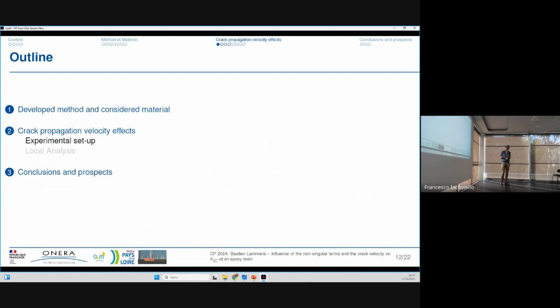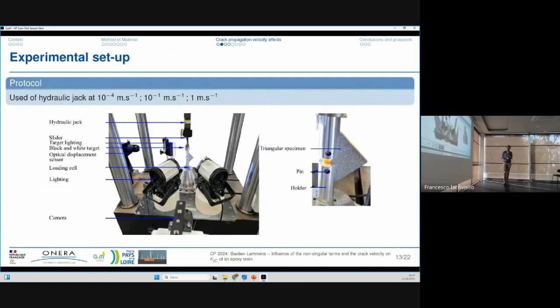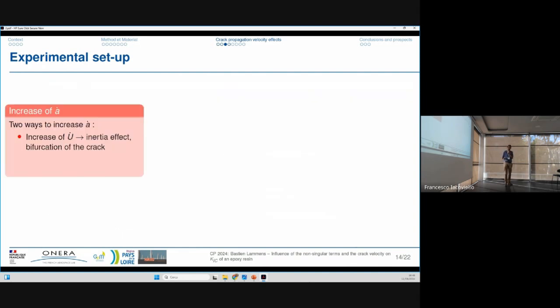I will focus only on the crack propagation velocity effect. So we used hydraulic jacks with different loading rates to have different crack propagation velocities. We have a high-speed camera and the lighting. And we use the triangular specimen with a speckle pattern, with black and white paint, to use digital image correlation. However, with these loading rates, we have only high-speed crack propagation up to 200 meters per second.